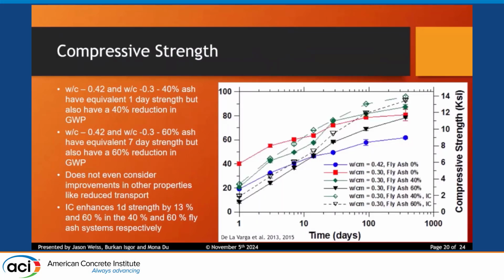So if I do that, and I've got now a log scale plotted along the x-axis, the blue line is the conventional mixture that the DOT would be using. And if I simply start replacing fly ash in the system, right, and I change the water to cement ratio a little bit, what I'll notice here is all of a sudden just the fly ash replacement, I can start getting equivalent strengths at different ages. So I can get a similar strength by changing the water to cement ratio in that system because I'm changing the gel to space ratio.